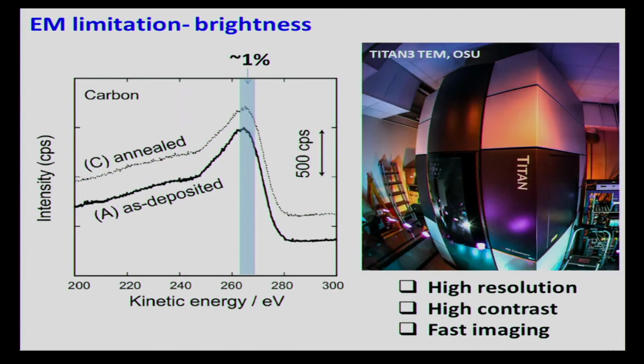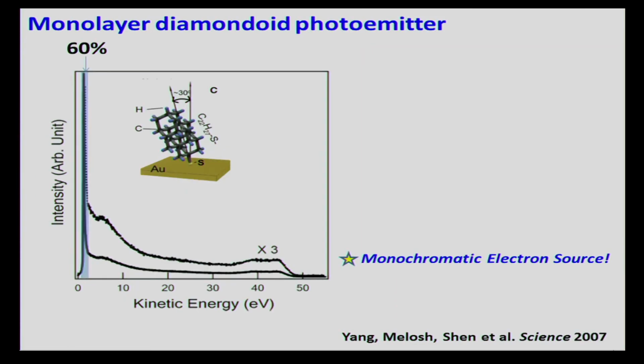So instead of this really broad distribution of the energies coming out of the surface with the diamond, with the diamondoid, what we have is a really sharp, almost monochromatic, that is single color, peak as a function of the kinetic energy. This single peak takes up about 60% of the total electrons coming out of it.